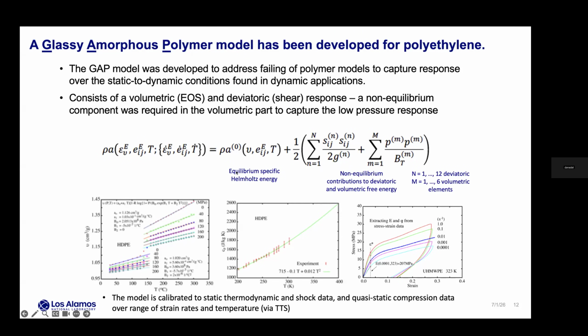It could be a Mie-Grüneisen form, or in our case we use one of the forms that's used for polymers, a Tait equation of state. And then there's a non-equilibrium form, which is related to the Maxwell elements. And so we parameterize this model based on quasi-static data as well as thermal expansion data and stress-strain data to get the deviatoric components, and then we can use that to simulate the shockwave profiles. I think I show an example later on, but it's that deviatoric component that allows us to capture that rounding in the wave profiles.